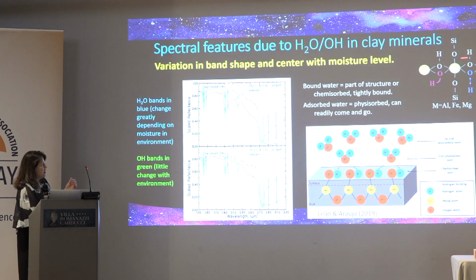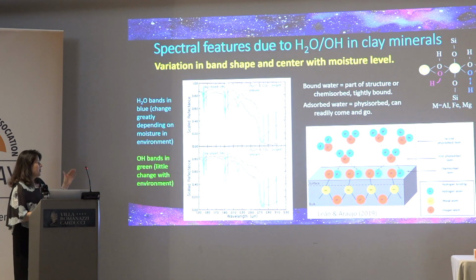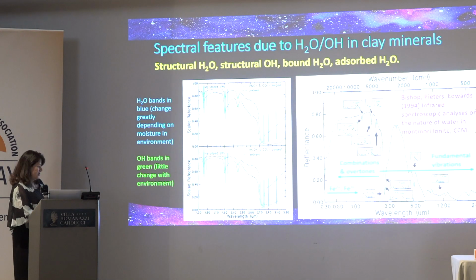So again, for the structural OH, those band positions depend on the type of cation, whether it's aluminum, iron, or magnesium. And those are these green bands here. And then for any surface, you're going to have water molecules that are adsorbed on the surface if it's a charged surface, and then there'll be the first layer and outer layers. So that's also happening with clays and with smectites in the interlayer region as well.